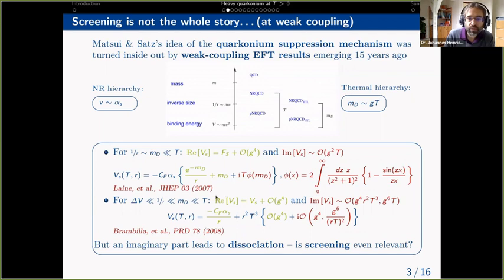And this calculation found that at such short distances, the real part of the complex potential is just the vacuum potential up to higher order corrections, and the imaginary part has this g to the 4th or g to the 6th dependence on the gauge coupling, and here also some formally different R dependence and temperature dependence. And so what this tells us is that the weak coupling says that these dissociation effects due to these non-zero imaginary parts, even at very small distances, are important.